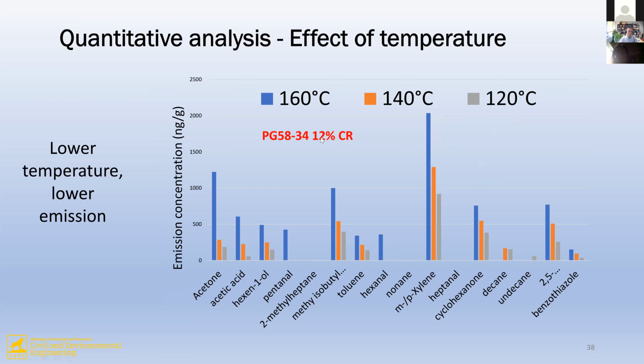So basically this one is only 12% rubber inside, okay? So it's 12% rubber, and basically we can reduce the amount of emission if we are able to reduce the temperature. Of course, in order to reduce the temperature, we have to do something else, right? Basically, we cannot just randomly reduce temperature. We reduce temperature by using some foaming agent, for example water, or some other chemicals. And so we can reduce the operation temperature so that we can have less emission.